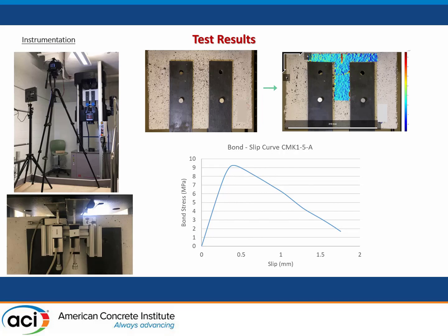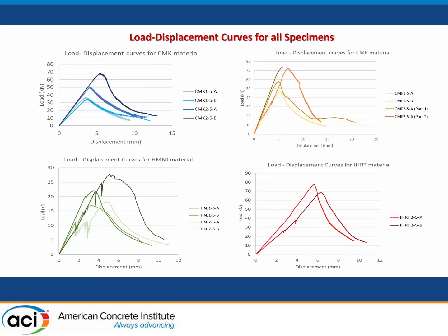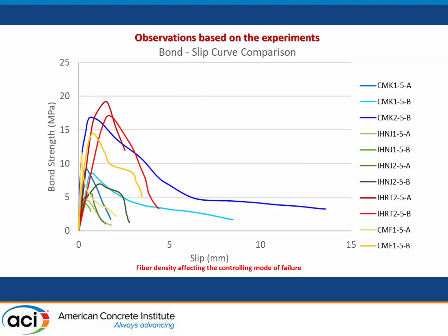A few duplicates were done for each typical test. And then, this is just a sample of the load displacement curves that reflect actually the bond slip curves that we obtained. We found generally that the specimens with a thicker cover were able to develop much larger bond stresses, and this is the typical bond stress slip loads that we obtained for the bunch of the specimens.